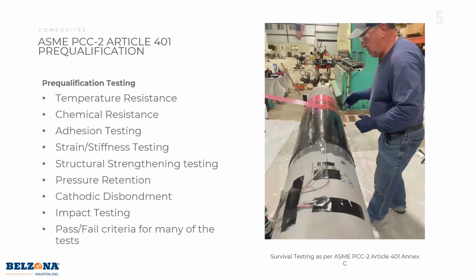Then when you look at the composite as a whole, because we are combining two different materials, that's what a composite is. We combined one material with another. So the carbon fiber is combined with the epoxy. Together, it's going to have a certain strain and stiffness, structural strength value, a pressure retention, an impact resistance. So we have to do a whole set of testing. Some of them are pass-fail. Some of them just give you a value. In the end, you can use them in the equations to determine the output of your repair.